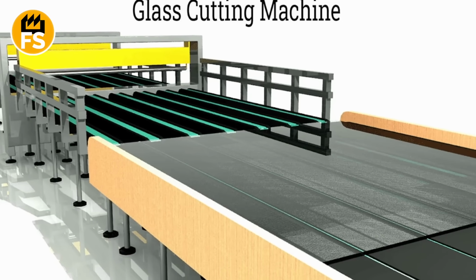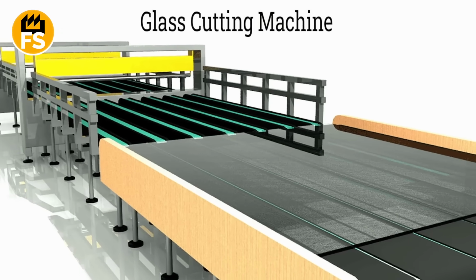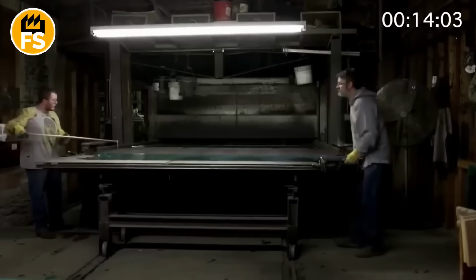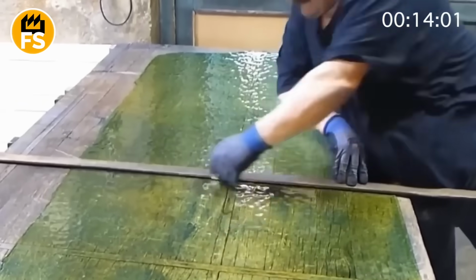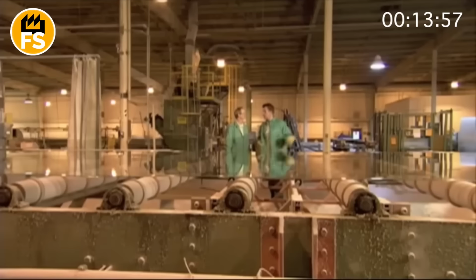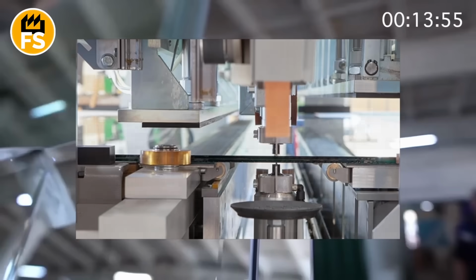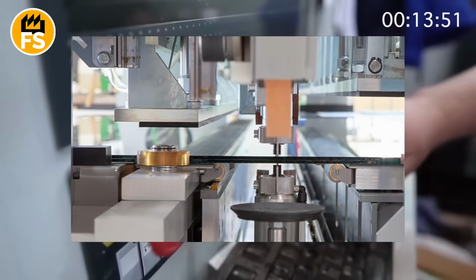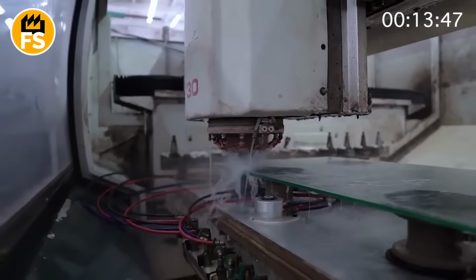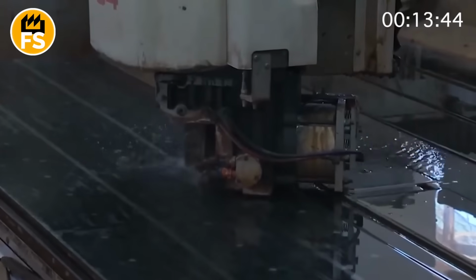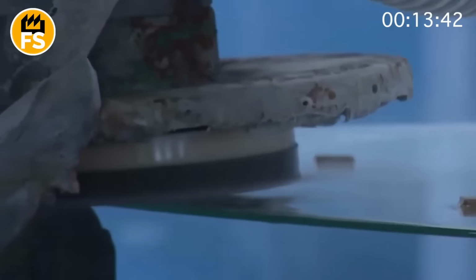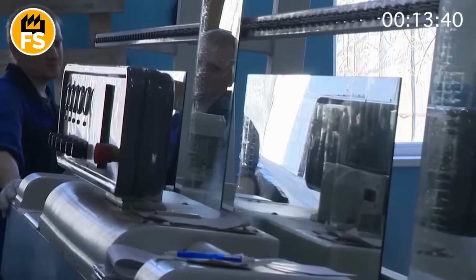Before it's cut, a computer scanning system analyzes the entire surface, looking for microcracks, inclusions, dust, stress. Any finding, and the sheet is rejected. The rule here is, better to reject early than to have glass explode in a truck or a shop window. Cutting is not mechanical, like in the old days. Now, it's laser or roller scoring. A microblade, similar to a diamond one, makes a line, and then gentle pressure breaks the glass precisely along the trajectory.